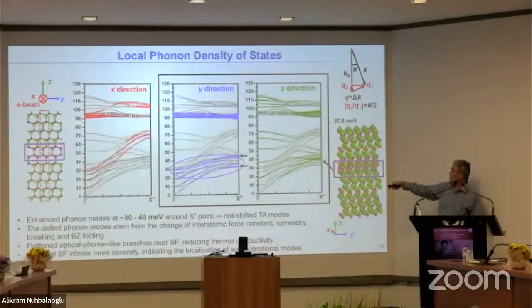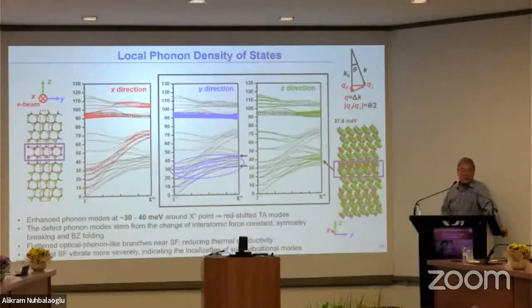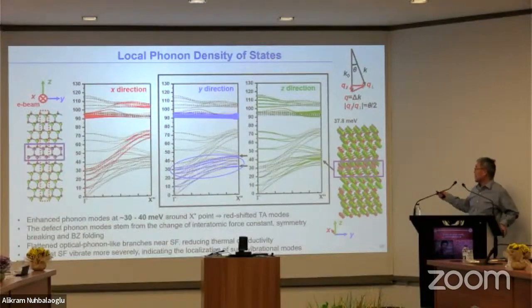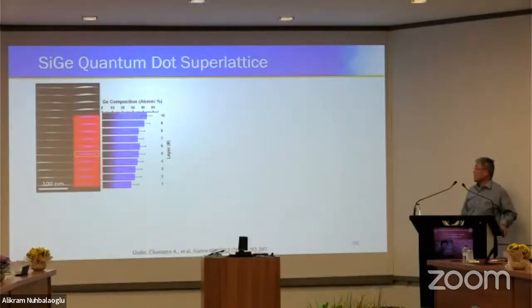And then there's a new mode at the stacking fault that forms. And this new mode contributes to the density of states of phonon. That's why we see the new phonon modes and also the change of the phonon energy across the interface. Right. That was a great example for the single stacking fault effect.